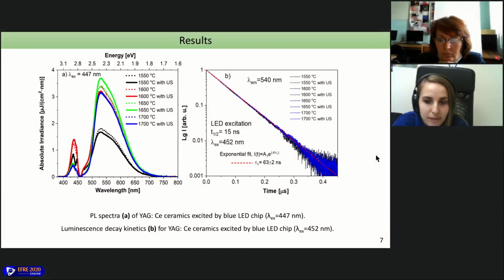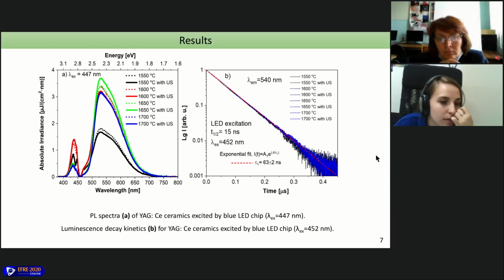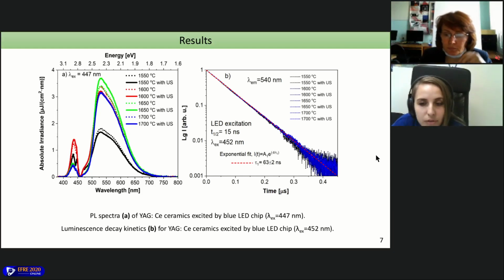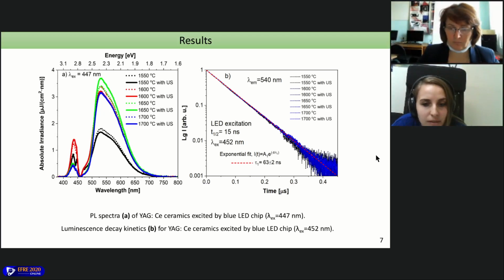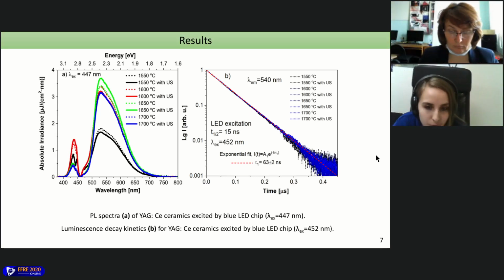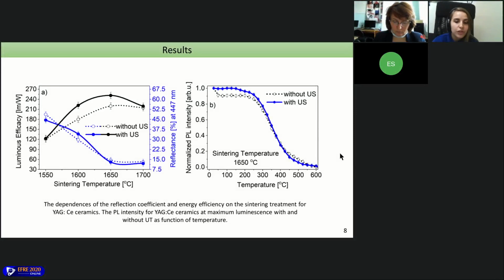So luminescence spectra in the spectral region of 400 to 800 nanometers of YAG with cerium ceramic sintered without and using treatment by ultrasound were excited by a 447 nanometers LED chip. There are emission bands in the ultraviolet and in the visible spectral region of YAG ceramics at different sintering temperatures. So the luminous efficiency of excitation conversion into visible light is the main characteristic of the phosphor ceramics and necessary for its use in the light source.